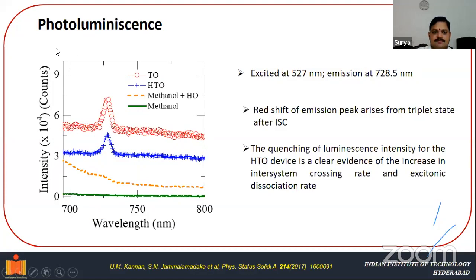We also performed photoluminescence experiments. Here we excited at 527 nanometers, and we detected the emission at 728.5 nanometers. What we could see is that this blue color, for the HTO device, shows quenching of the photoluminescence in comparison with the titanium dioxide. What can we understand from this? The quenching of the luminescent intensity for the HTO device is clear evidence of an increase in the intersystem crossing rate and excitonic dissociation rate.